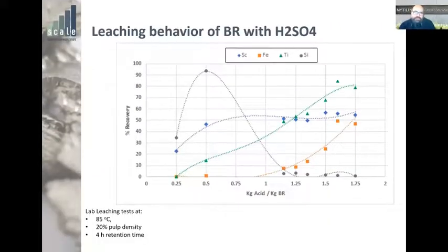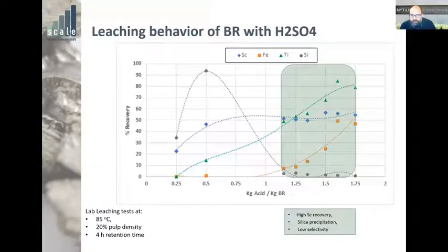So let's see a bit the leaching behavior of bauxite residue with sulfuric acid in the case of the Greek bauxite residue. And we did the lab test here with a very simple setup, starting with 85 degrees, 20% pulp density, and 4 hours retention time. And you see here the recovery of the various elements in relation to the kilograms of sulfuric acid per kilogram of bauxite residue. There are 3 different regions in this graph. The first one is when we have high scandium recovery. You see it's above 50%. We have silica precipitation. We don't have any silica in the solution because of the high acid. But we also have low selectivity. As you can see, titanium is nearly at 80% and iron is nearly at 50%.